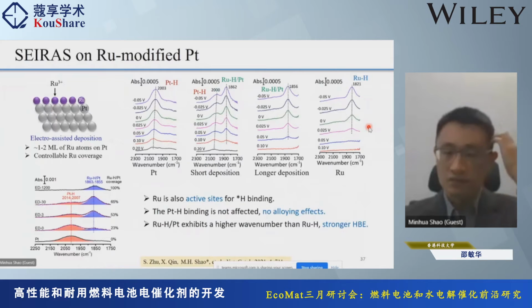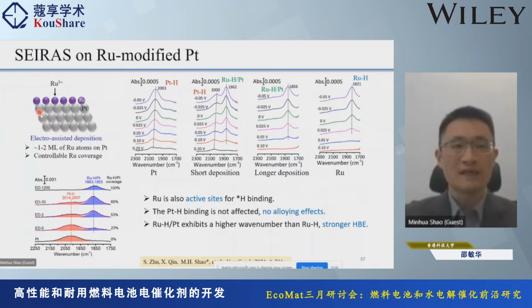But we found that this is actually not true, because what we did here is put ruthenium on the platinum surface. By changing the coverage, we can monitor the platinum-hydrogen bonding and the ruthenium-hydrogen bonding at different coverages of ruthenium. So here is pure platinum, and with different deposition times, we see the platinum-hydrogen bonding, and we also see the ruthenium-hydrogen bonding, from which we can calculate the coverage of ruthenium. We can see that the platinum-hydrogen does not change at all in location, the wavenumber. That means platinum and ruthenium have no electronic effect. And ruthenium is actually also a very active site for hydrogen bonding, not only to adsorb oxygen.